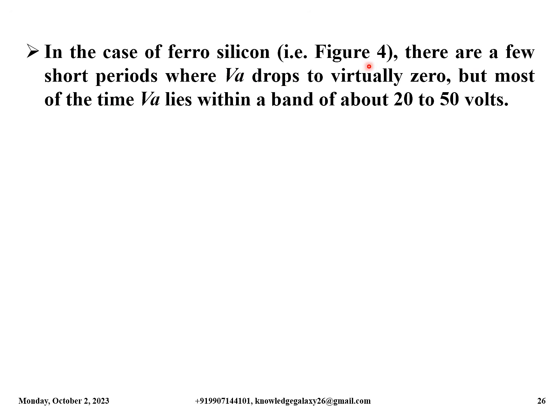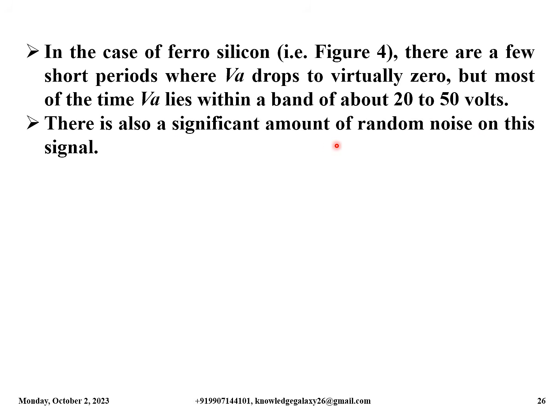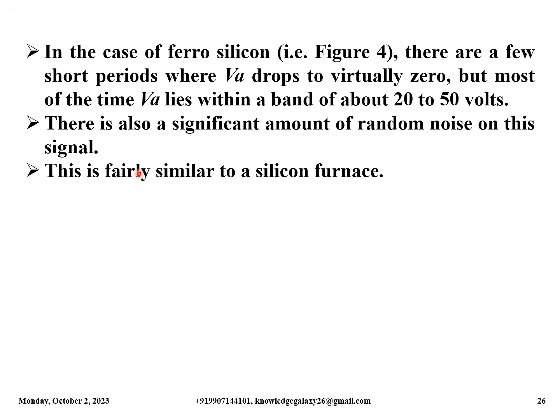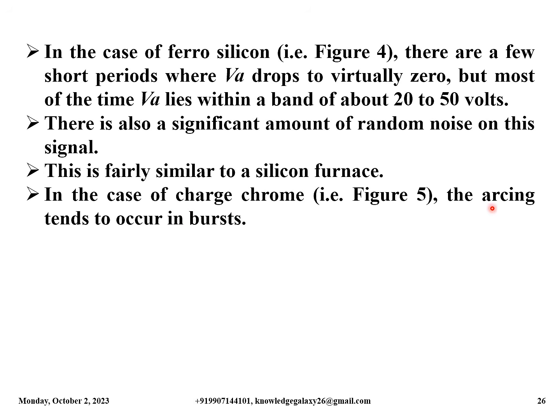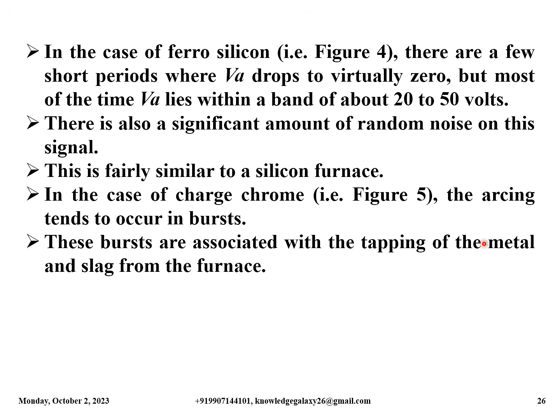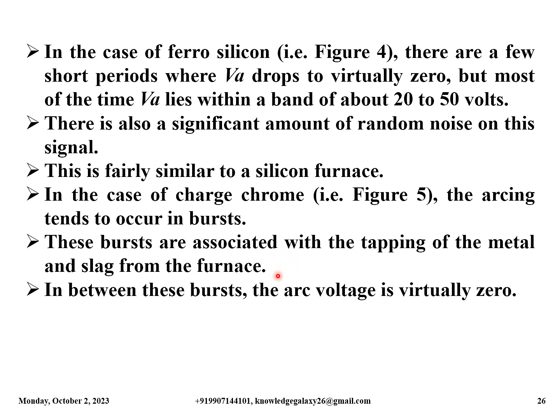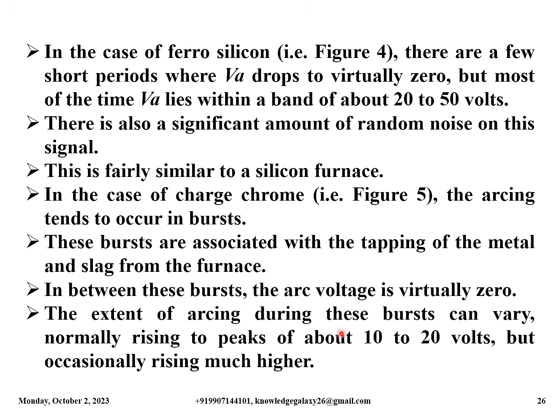In the case of ferrosilicon, that is in figure 4, there are a few short periods where VA drops to virtually zero, but most of the time VA lies within a band of about 20 to 50 volts. There is also a significant amount of random noise on this signal. This is fairly similar to a silicon furnace. In the case of charge chrome, that is in figure 5, the arcing tends to occur in bursts. These bursts are associated with the tapping of the metal and slag from the furnace. In between these bursts, the arc voltage is virtually zero. The extent of arcing during these bursts can vary, normally rising to peaks of about 10 to 20 volts but occasionally rising much higher.